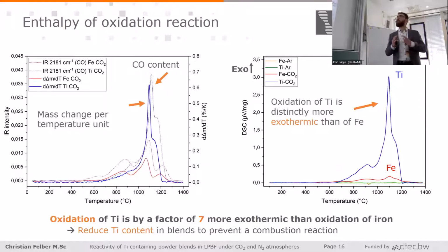And this is because we have here the dissociation of the carbon dioxide into carbon monoxide and oxygen. If you remember, we could see in the ignition product, I would say, that we have some carbides in there. So in this process, we had the participation of carbon here in the equilibrium plot. And more interesting is that exactly at the time or at the temperature where we have the highest oxidation rate, of course, we have also the highest heat release, because these oxidation processes are very exothermic.